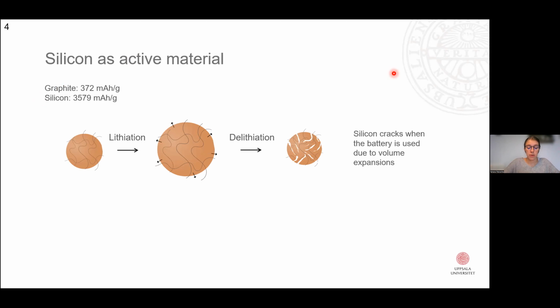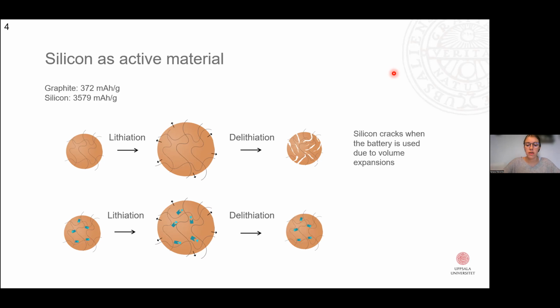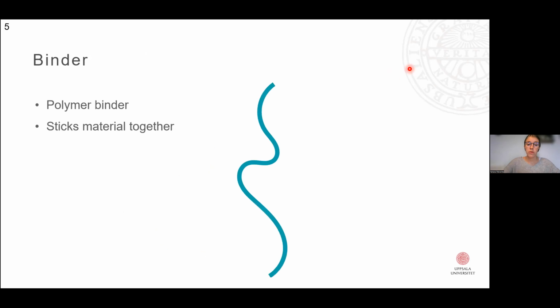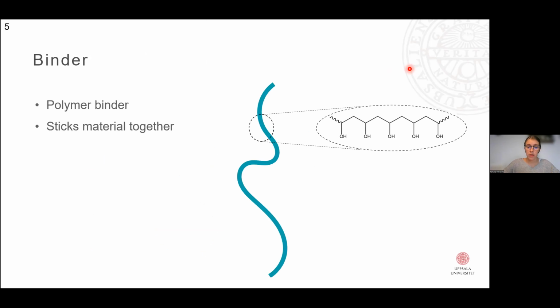And we need something to repair this damage spontaneously. And here is where the binder comes into play. So if we utilize the binder and add groups that can break and form along with these volume expansions, we can make the material hold better together and avoid these cracks. So we want to use the binder. The binder is then a polymer that sticks everything in the electrode together. But other than that, it doesn't really have any electrochemical function. So it's dead weight, and we want to use as little of it as possible.